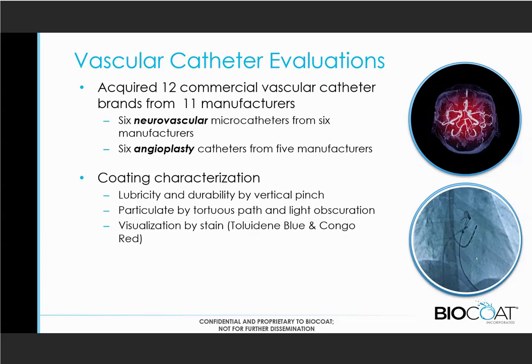What we did is bring them in-house and did a coating and characterization, where we were looking at lubricity and durability by the vertical pinch test that I talked about previously. And then we also did a particulate evaluation by using a specified tortuous path and counting the particles that we had collected with light obscuration. And then we did some staining of those to visualize that coating afterwards with either a toluidine blue or a Congo red dye.